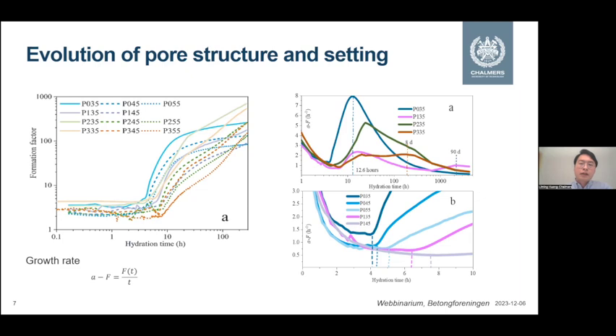In the figure on the left, we see that in the first few hours the formation factor stays almost constant, meaning there is very limited change in the volume of pore solution or its connectivity, so no significant structural change. To better analyze the structural change rate, we define the average growth rate of the formation factor as AF, the formation factor divided by the hydration time. On the right figure, we see the evolution of AF is somehow the same shape as the isothermal calorimetric data.